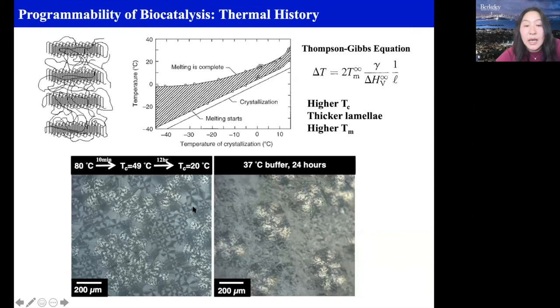So here is one example. We have one piece of sample. We just did two different thermal treatments. The large spherulites shown here are crystallized at a higher temperature, while the smaller spherulites were crystallized at a lower temperature. So you can see in one sample, by simply modulating the thermal history, we can get this region, the small spherulites, to degrade very rapidly, while we can maintain the other part not to degrade. This really provides a guideline for how the polymer should be processed, so as to program the degradability.